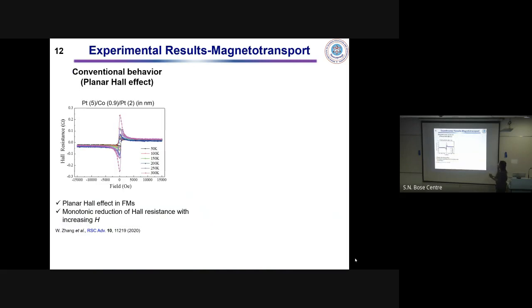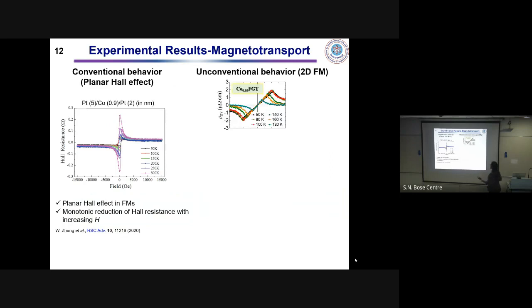Now, in order to probe further, we try to explore why I am calling this an unconventional behavior. If we consider a ferromagnetic system, this geometry of measurement is nothing but planar Hall measurement. You can see over here, the magnetic field is applied in the plane of the sample. When the magnetic field is 0, you have a finite value of Hall resistance, and when I increase the magnetic field, it continuously decreases. However, what we have observed is something opposite.